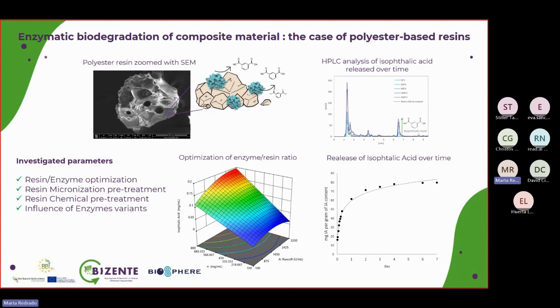In order to understand better the reaction mechanisms and improve the degradation yield, several approaches were followed. Those studied, for example, the optimal ratio between the resin and the enzymes. Also, we studied how the pretreatments, both chemical and mechanical, affected the process, as well as the influence of some variants of the enzymes in the process. For example, the temperature. Thanks to this P6, we could see that reaching higher temperatures will improve the process, and we could achieve it thanks to the last mutant. But also how long the process needs to be working in order to reach the peak. After testing these several approaches and a continuous improvement, a maximum release of isophthalic acid per gram of resin treated was defined, as you can see in the graph at the bottom right.